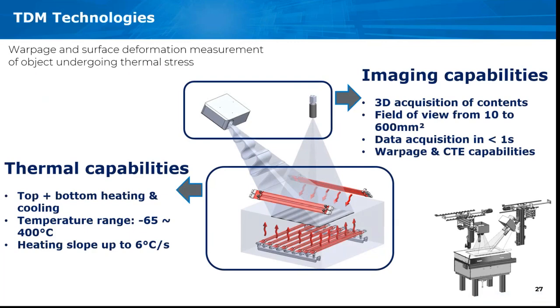So Insidix is providing TDM equipment, which is basically composed of two parts. One part is a 3D sensor, which has imaging capabilities. This is a projector and a camera combined together, which allows taking 3D measurements of whatever is inside an oven. It can be a small sample from 10 by 10 mm up to 600 by 600 millimeters square. And it can provide warpage and CTE measurement.